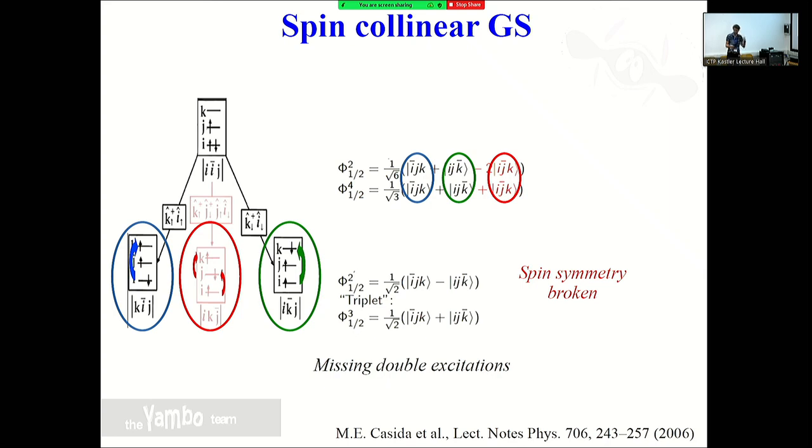In the quantum chemistry community, this problem is very well known, and there are references from that community. In the community of extended systems, we usually don't care much about that, and the reason is that the total spin of the system is usually not so important as a quantum number, especially because magnetic materials are usually metals, and then you cannot really define the total spin. But one should keep that in mind, especially if you study, for example, defects in extended systems where you can have some kind of isolated physics, or if you use the BSE for molecules and you have a magnetic molecule, then this is an issue.